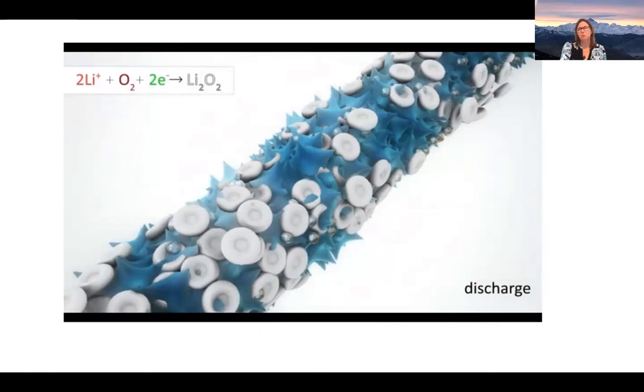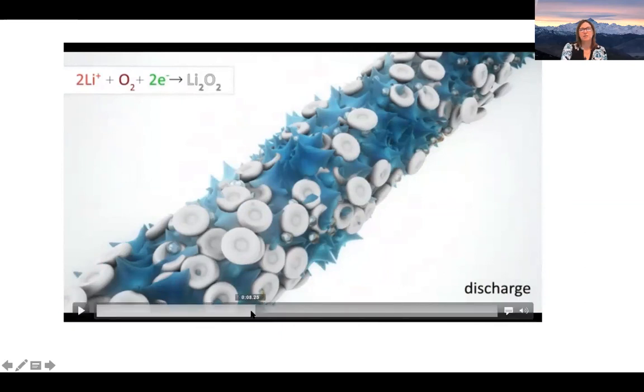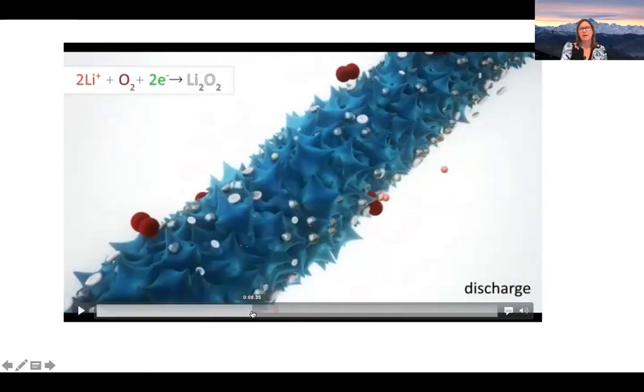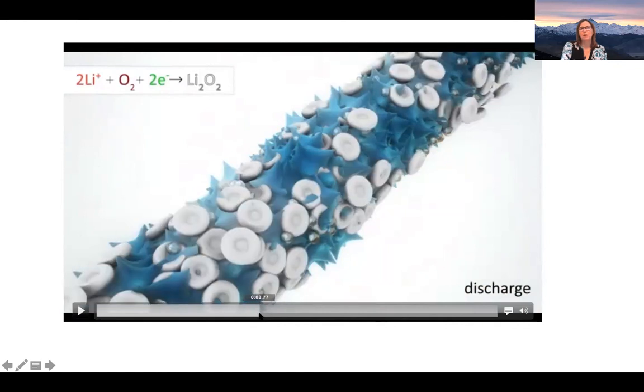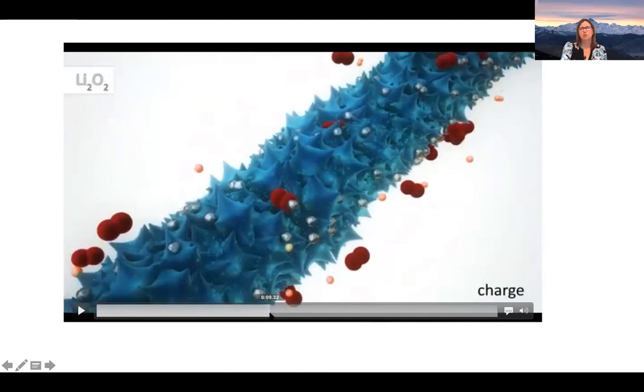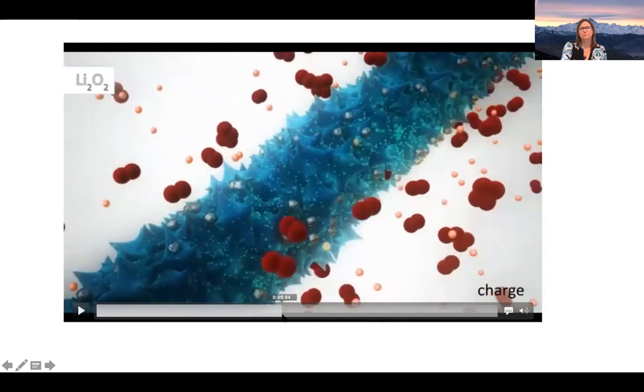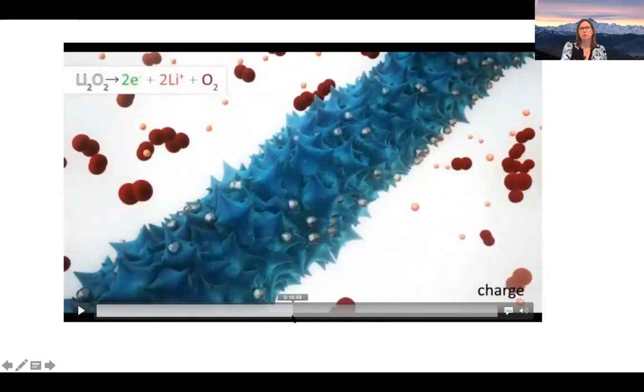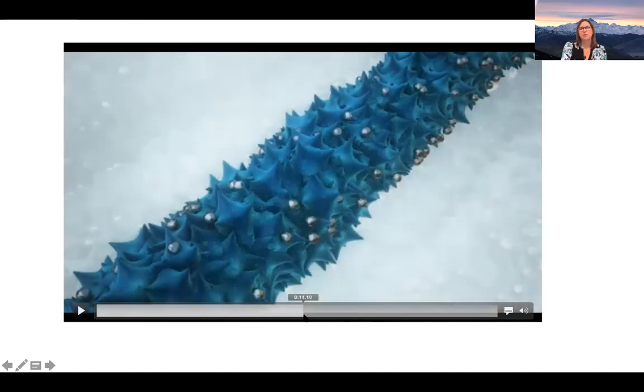And one of the problems with these kinds of batteries is that we would get stuck in the discharge product and make it non-reversible. And so our material was much better at making a reversible reaction. So here's the reversible reaction, where you have the lithium peroxide plus 2 electrons plus lithium going back to oxygen again. And you need this to be a reversible process.